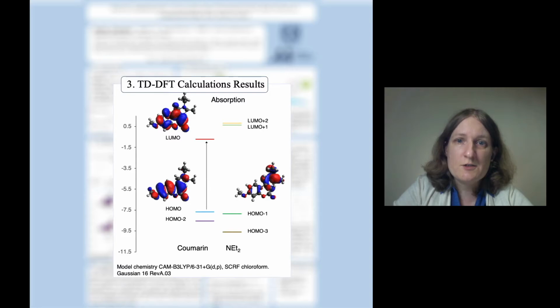TDDFT calculations were performed on the Coumarin derivative to investigate the quenching mechanism. The energy level of the lone pair of the amine moiety was slightly lower than expected for a very efficient PET quenching. However, its participation in the transition state was sufficient to explain the experimentally observed results.